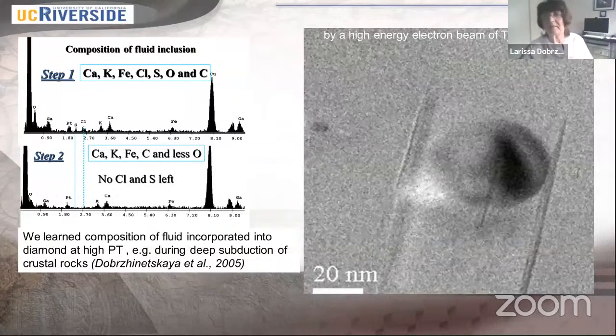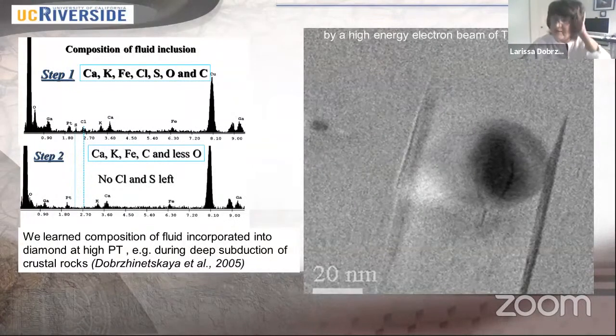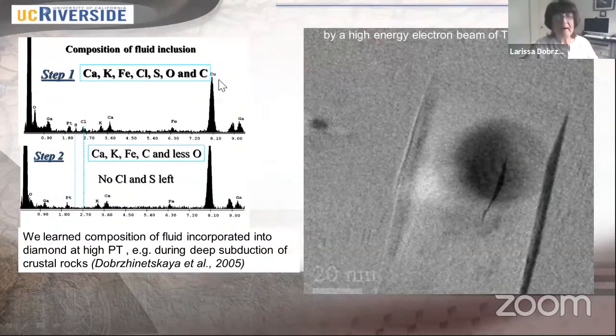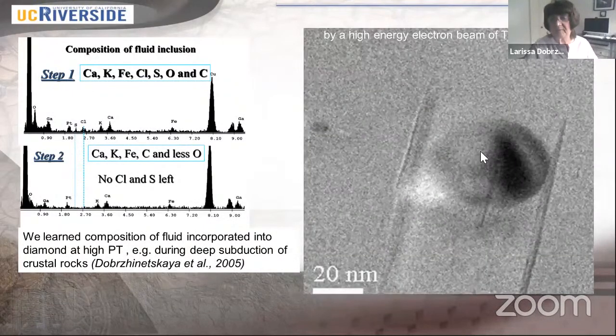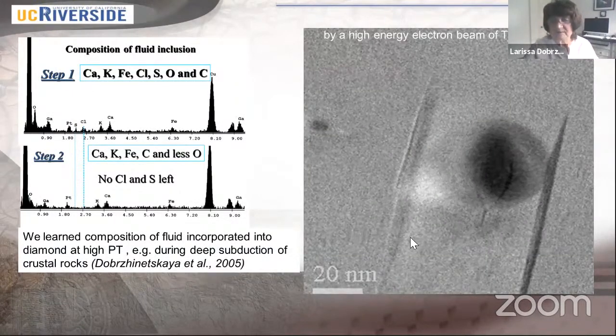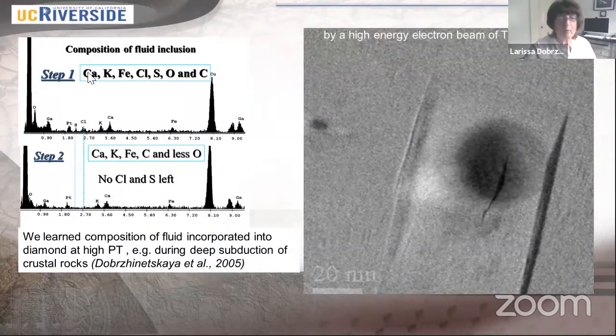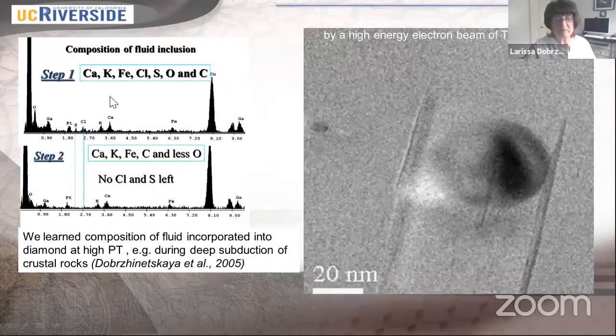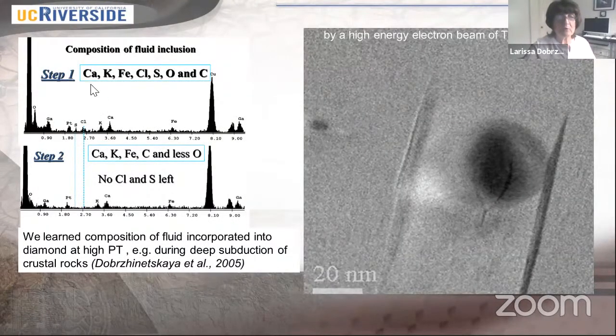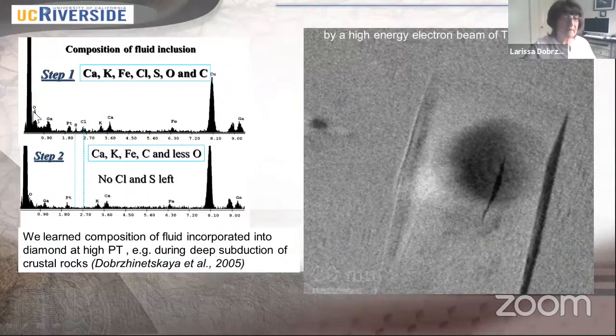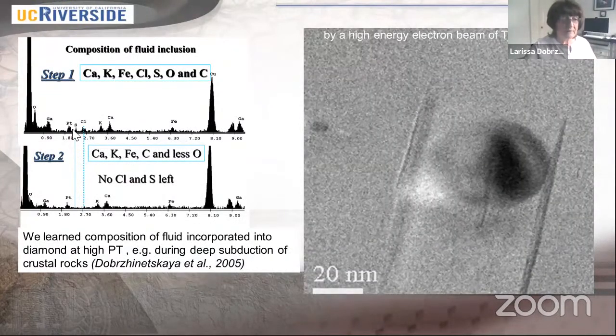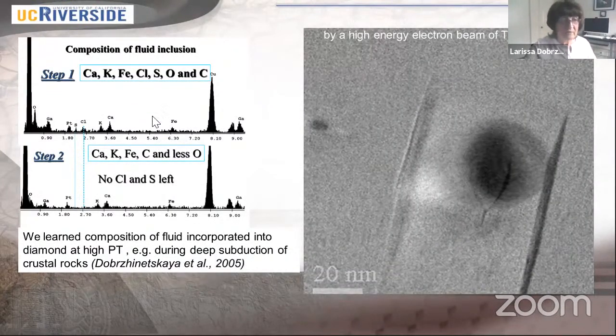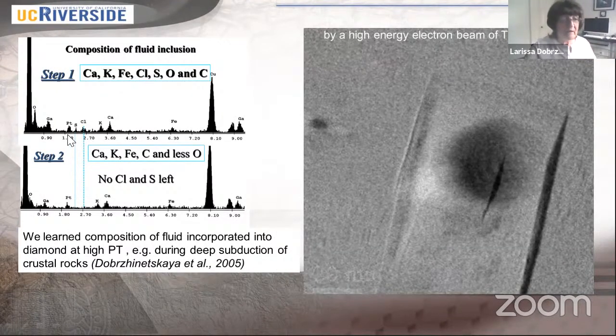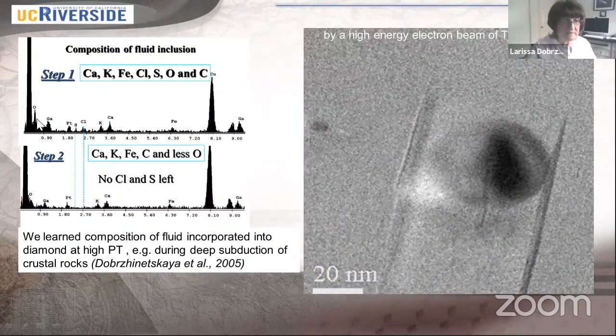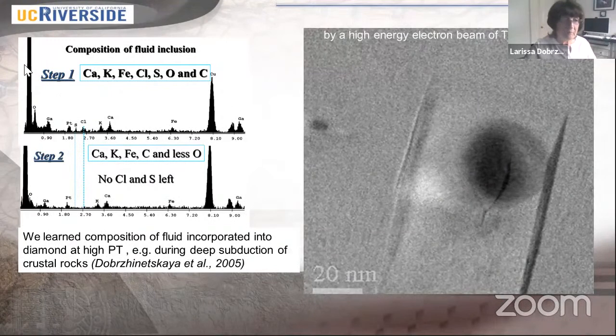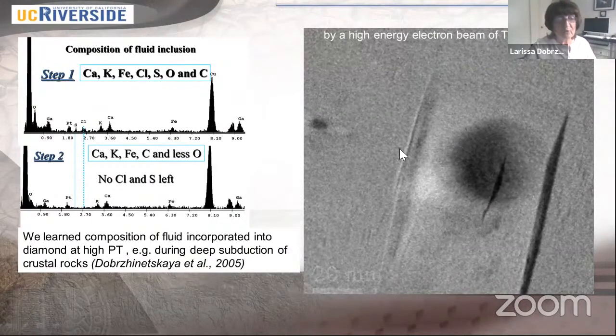It was a very exciting moment and very new for us as well. So we had a chance to measure composition when the inclusion was alive. And we found with the EDS spectrometer, which is available in the transmission electron microscope, that there is calcium, there is potassium, there is iron, there is chlorine and sulfur and oxygen and the carbon, of course, in this fluid.